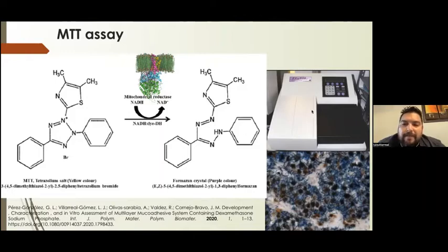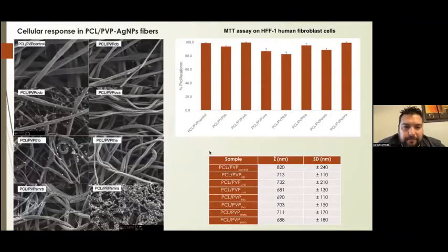So when we have a high absorbance value, we can say that the cells are viable after the exposure to the fibers. And if we observe a decrease in the absorbance, we will relate it to the loss of viability after being exposed to the fibers, always comparing with the normal growth without any exposure.